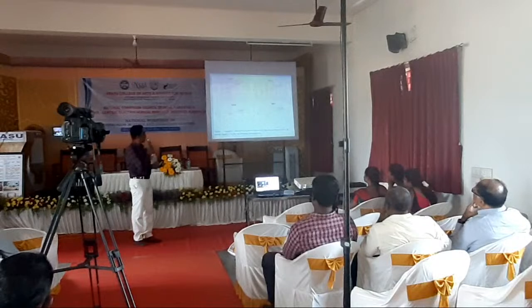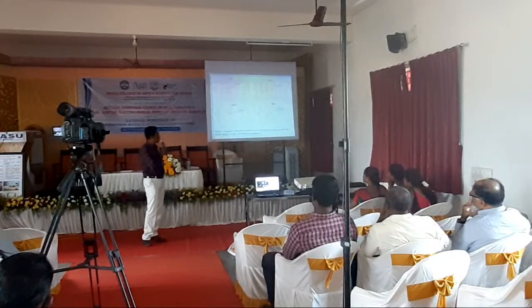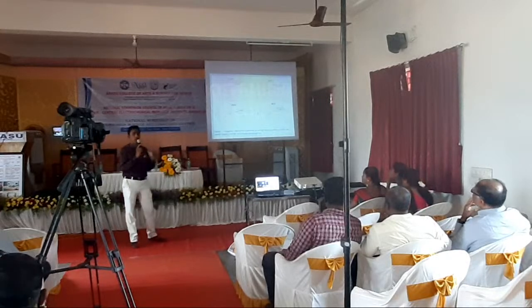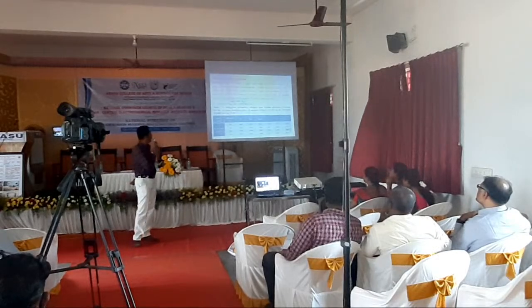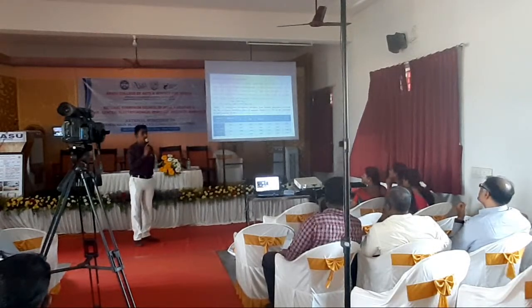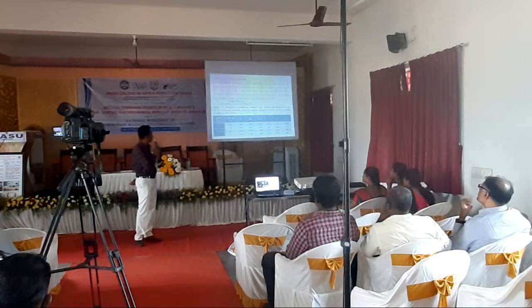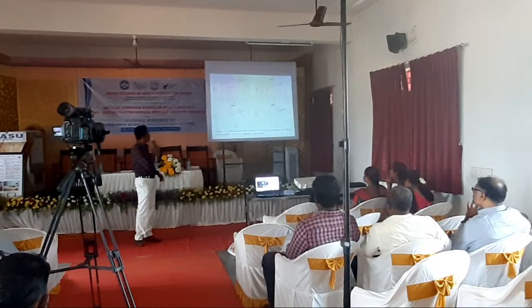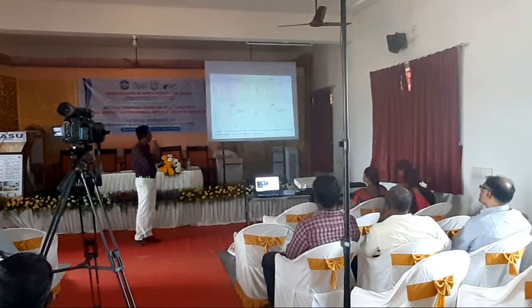The Langmuir adsorption isotherm curves are displayed for the adsorption of Carissa carandas plant leaves on carbon steel in 1 normal hydrochloric acid at different temperatures: 303, 313, 323 and 333 Kelvin. But the highest inhibition efficiency is at 303 Kelvin. Temkin adsorption also, just like Langmuir adsorption, shows 303 Kelvin as the highest adsorption efficiency. The Temkin adsorption isotherm curves are displayed. So this also shows 303 Kelvin has the highest inhibition efficiency.